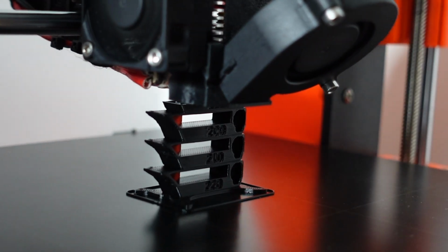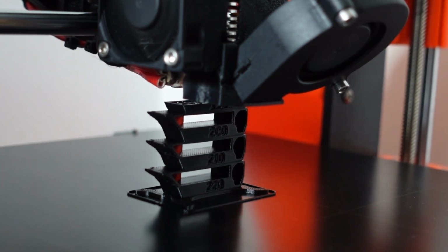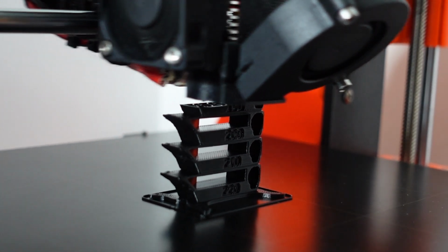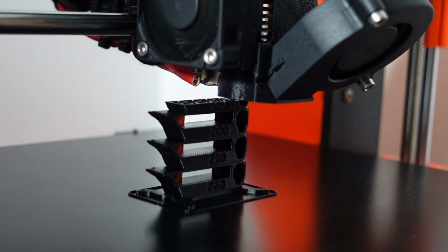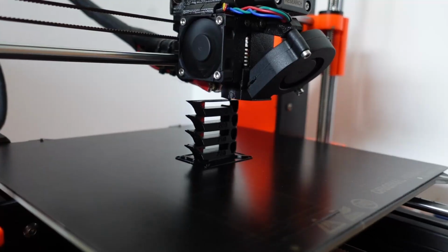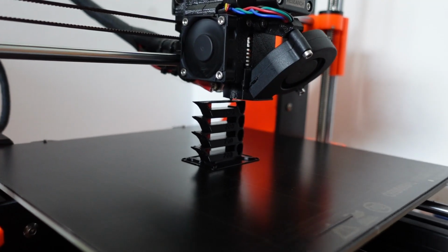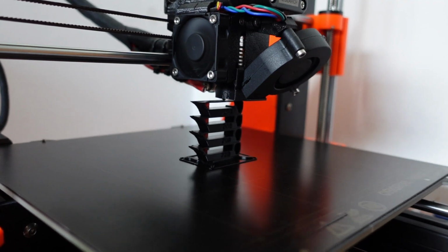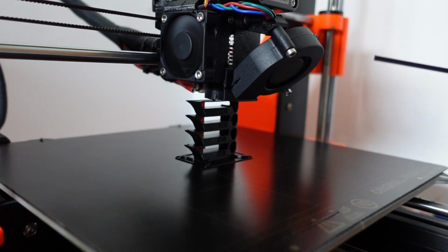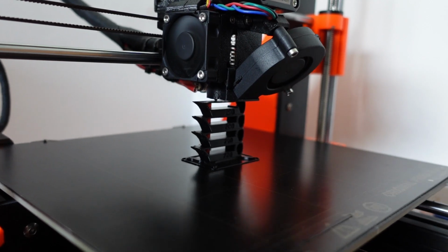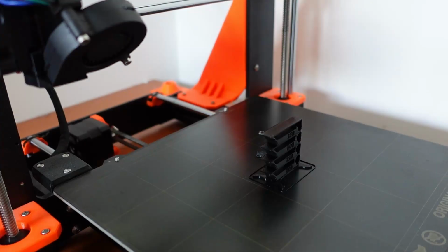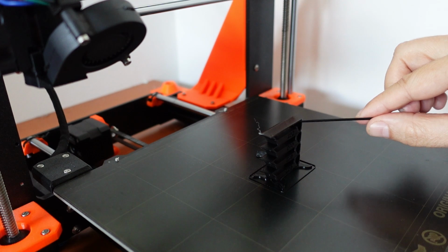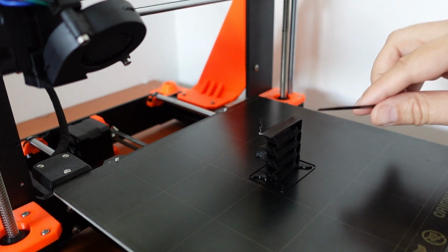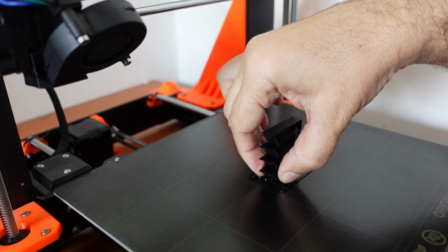This is the last element at 190 degrees Celsius. The printing looks okay. Only once so far I heard a click from the extruder, probably more resistance in the nozzle. Maybe you can hear now the clicking of the extruder. So definitely this is too low a temperature, but I will let it finish now. Okay, the printing is finished, and I can see the last element was not printed correctly, but I will show you that in a few seconds. First I want to check the bed adhesion.